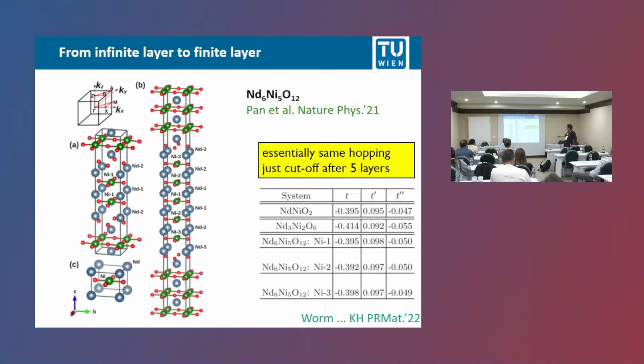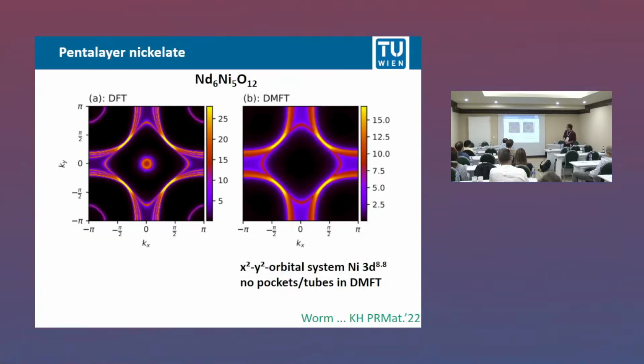Let's briefly go from the infinite layer to the finite layer compound. So Giulia Mundi has grown these 5-layer nickelates with 1, 2, 3, 4, 5 nickels, then a Ruddlesden-Popper spacing layer, and then another 5 layers. As you see here, the hopping parameters are virtually the same. That's very different from the cuprates because it's not bulk systems. All of this has been grown on a strontium titanate substrate. And because of that, the 5-layer system is very much alike.